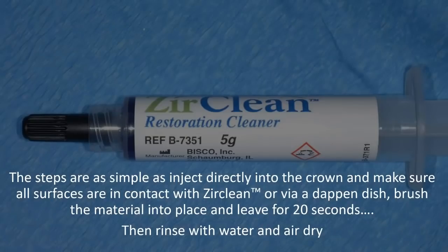Zirclean, the steps are as simple. It's 20 seconds, and I like to scrub and make sure all the surfaces come in contact with Zirclean. You can put it in a dappen dish and brush it. In fact, we use the Viscostat brushes. We absolutely love the brushes. They go directly on this. We just scrub the crown for 20 seconds and rinse, and we use an air-only dry. So air-only syringe, and we dry the crown. Both are great materials, both.